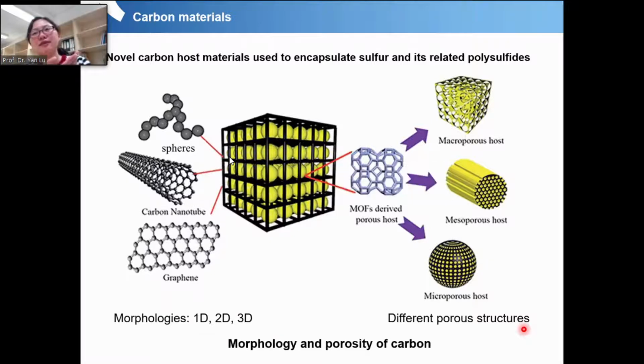So Professor Linda Nazar is the first. She gave a concept using porous carbon. And of course, in that case, the porous carbon has very good conductivity, and also due to its porous structure, it can give physical confinement. That's why she was the first to get very promising performance for the lithium sulfur battery. And I'll just give you an overview here.